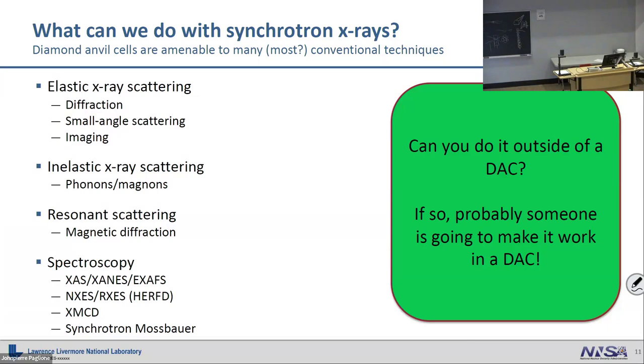The very first things that were done with X-rays were diffraction. Like I mentioned before, if you grow your crystal, you've got to do X-ray diffraction. The community expects you to have a diffraction pattern with your sample. Same thing is true: a lot of the DAC work in the 80s used a lot of laser things, Raman. So you have these inferred structural phase transitions because of symmetries, but if you do something like Raman scattering, there are lots of positions in the atomic structure that just aren't Raman active. You're just not sensitive to them at all, but with X-rays, you're sensitive to all of them, provided you can scatter off of them. So hydrogen, not so much. And that's about it at the synchrotron these days.